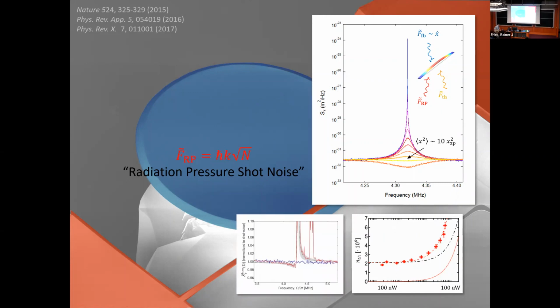where radiation pressure shot noise starts to overwhelm thermal motion, you would see that the optical field is getting squeezed a little bit. This is because whenever there's an intensity fluctuation in the light field, it gives rise to a displacement fluctuation of the mechanical resonator because of radiation pressure, which gets written onto the phase. So the mechanical oscillator starts to act like a low noise Kerr medium in this regime where radiation pressure shot noise dominates. And that can give rise to an effect called ponderomotive squeezing, which was a big driving impetus for quantum optomechanics back in the early 2010s.